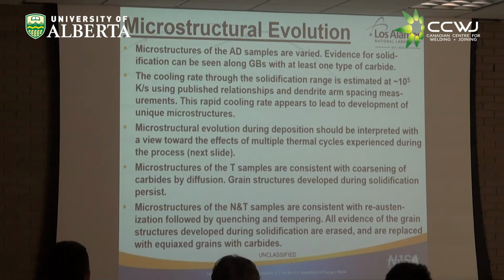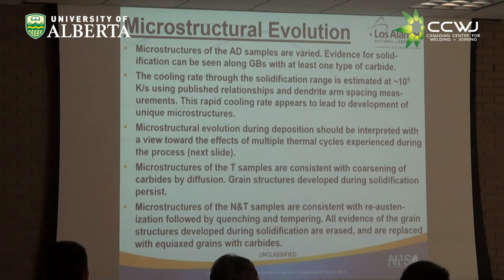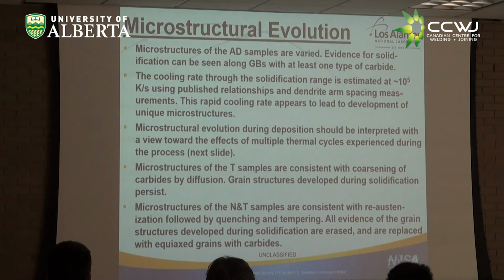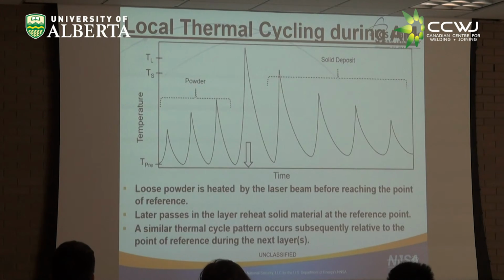You can also use the numbers for steel, which give cooling rate as a function of primary dendrite arm spacing, as a function of carbon content. If you use those two, neither of which this is, you get a number on the order of 10 to the 5th K per second using published results for primary dendrite arm spacing. So it appears something going on here leads to development of unusual microstructures.